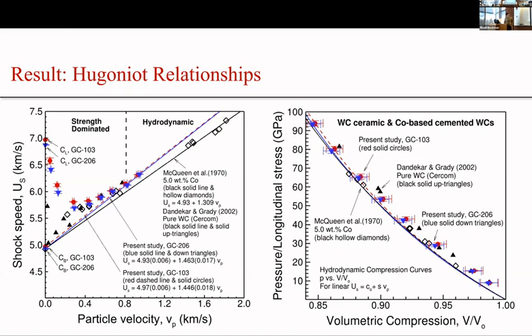So to obtain such a linear Us-Up relationship for the tungsten carbide samples, we can only use the highest two stress level data points, where the ratio of the shear stress and the pressure is very low to negligible. And also we assume that the linear Us-Up curve intersects the y-axis at the ambient bulk sound speed, represented by these two data points.